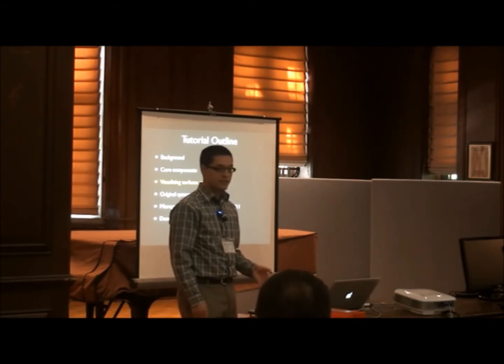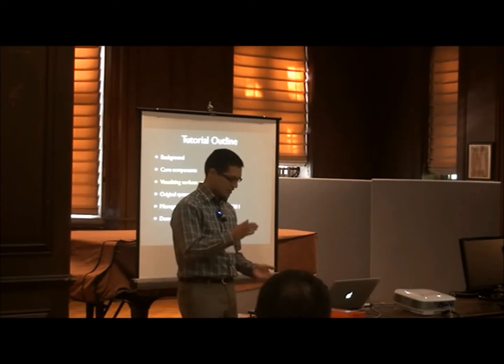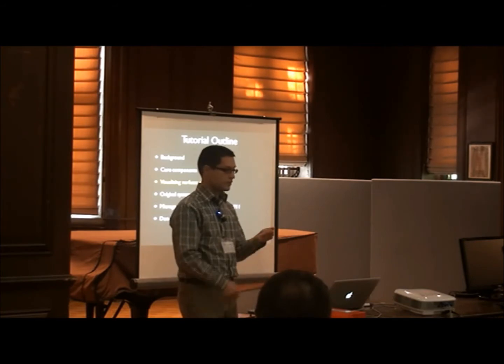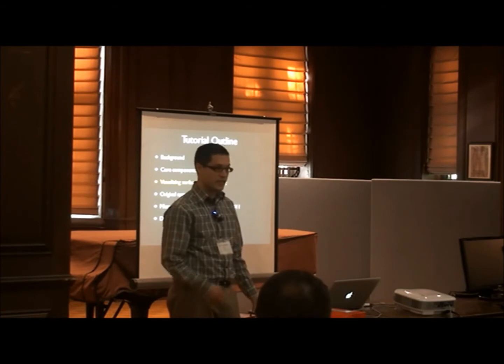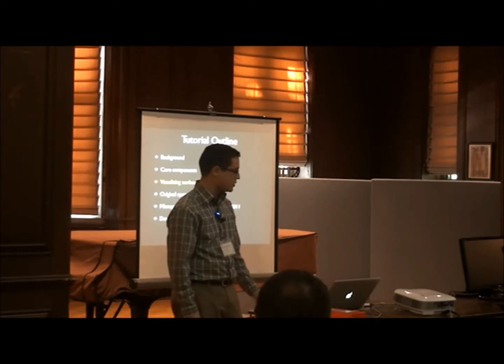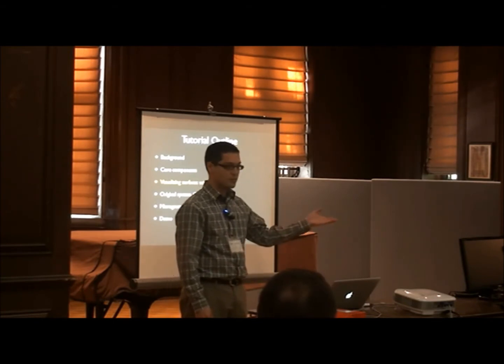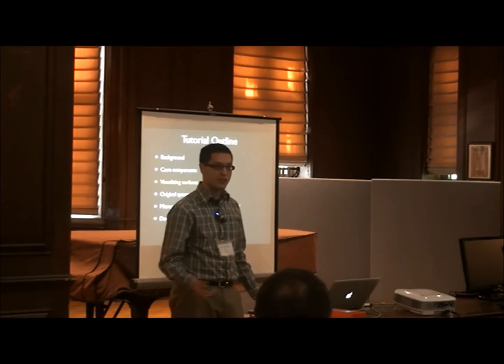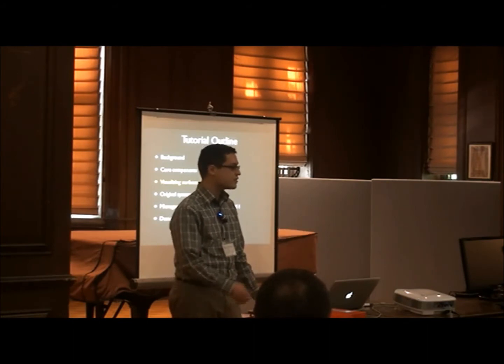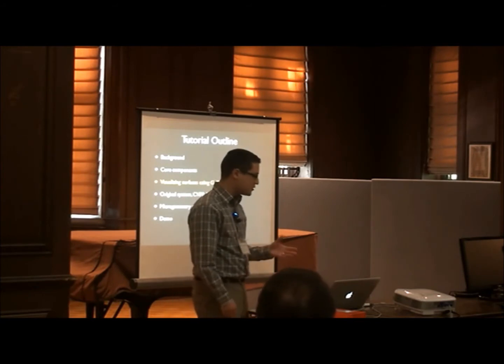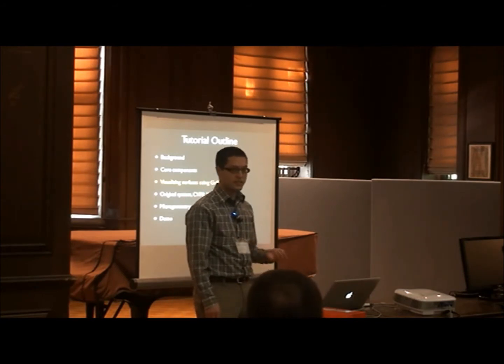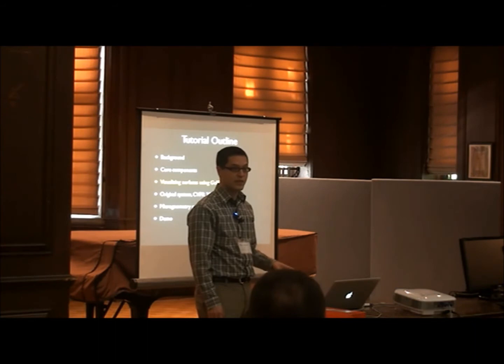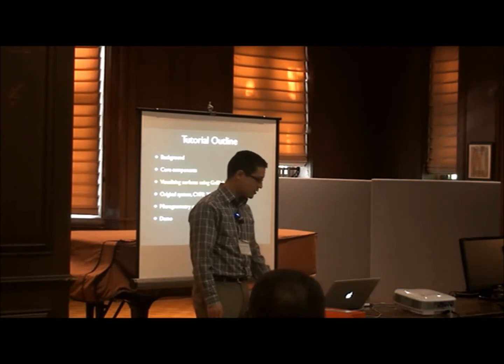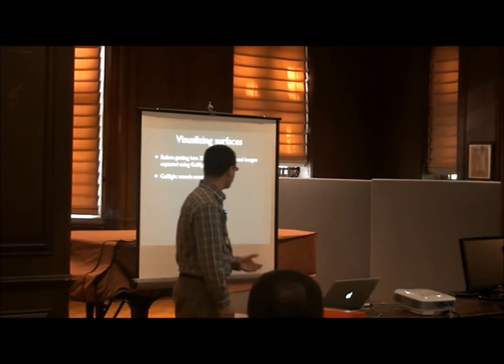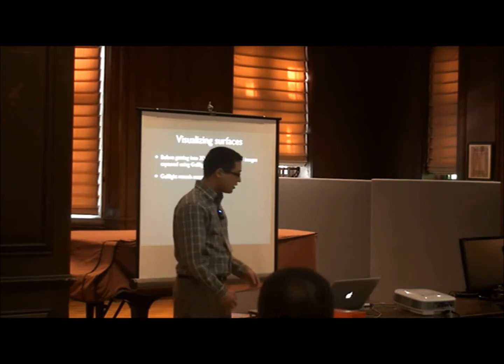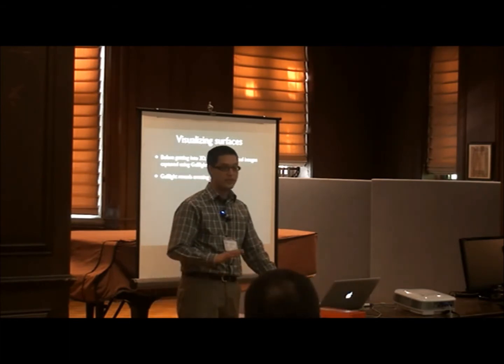Yet GelSight is significantly simpler in the sense that it's non-destructive. We don't have to coat it with gold, and it doesn't have to be done in a vacuum. As you'll see, we can just stick a piece of gel on a sample and get images that are SEM-like in literally seconds. So that's been interesting to me to learn that, in fact, just seeing a surface in this way has value already. We don't need to do the measurement. And that's really where this gallery comes out. It's a lot of cool images done using GelSight, and this is not 3D.